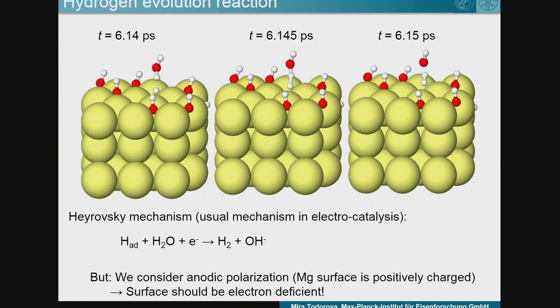Now we looked at the geometries that are associated with the formation of these hydrogen molecules, and here are a few snapshots from the MD. What you can see here is a hydrogen atom adsorbed on the surface, which is otherwise hydroxylated, and there is a water molecule approaching. The water molecule binds hydrogen in an unexpected geometry for people who are doing water, because they usually don't expect that the hydrogen will bind to a hydrogen. And then there is a dissociation, the hydrogen molecule is formed, which then eventually leaves the surface while the OH dissolves.